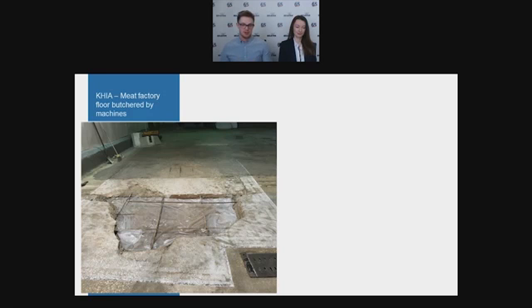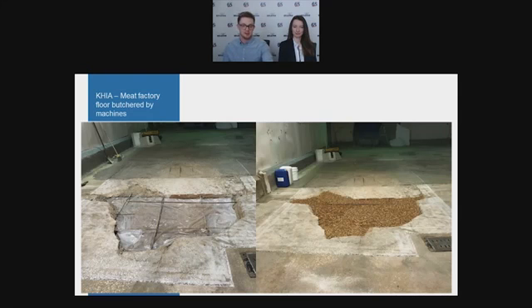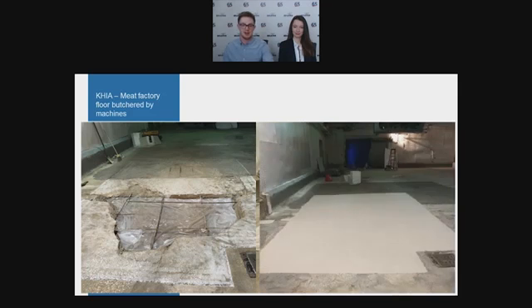In this case, roughness is not required because the surface was rough enough already. So you avoid the need to use machines which may incorporate difficulties in terms of hand-arm vibration values, or HAV values. So that was avoided completely. The product itself we used was Belzona 4154, bulk fill resins and an aggregate to pack out the main section of the repair itself. And then Belzona 4111 was applied on top of that surface to give you your mechanical properties, compressive strength, tensile strength, impact resistance, and general dilute chemical resistance as well.